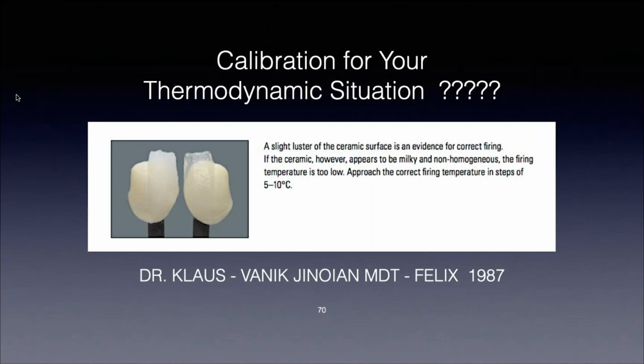So if you were to fire a pontic and some veneering material on the pontic, and then you did a real thin little crown, that porcelain is going to take longer for it to heat up, and it's going to take longer for it to cool down, and it may have a slightly different look. You have to accept that because of the mass difference between these units.